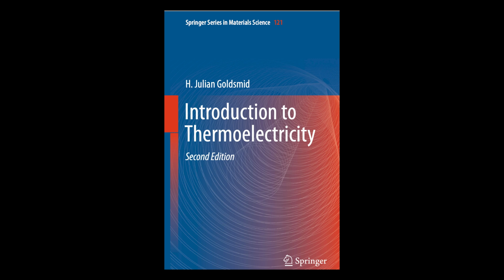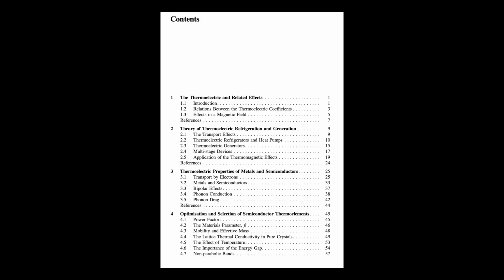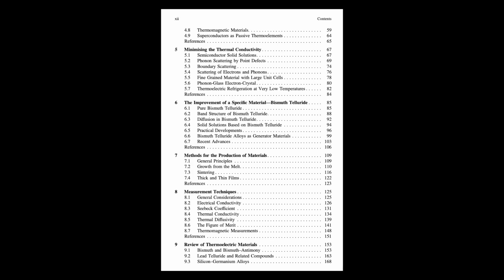And zone melting, how's that different? Zone melting uses a small molten zone that travels along a solid bar of the material. As it moves, impurities tend to get swept along or left behind, depending on whether they prefer the liquid or solid. Pass the zone back and forth multiple times, and you can purify the material or get a very uniform distribution of dopants. It can also help align grains in materials like Bi-Te. The doped zone technique is where you add dopant to the zone itself to get a precise concentration throughout the final bar.